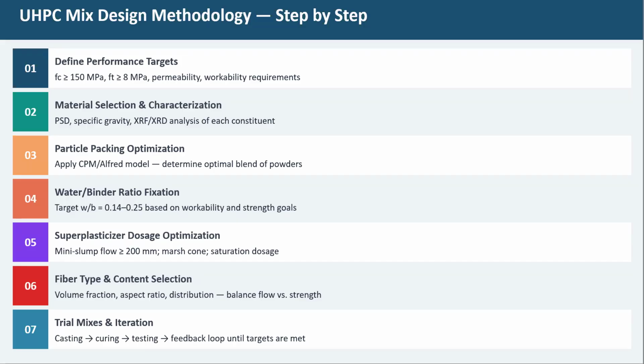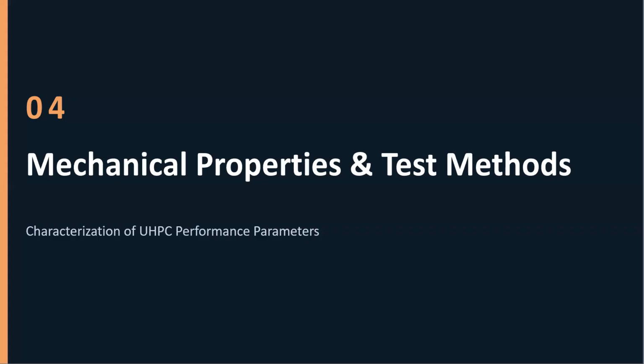That's again a bad sign of flowable nature of the UHPC, where you cannot attain easy flow, especially if you are focusing on self-compacting UHPC. And it is imperative to do multiple trial mixes, because it's not that in one trial we are going to get the entire properties or the desired characteristics of UHPC. It's an iteration of multiple materials, as with any concrete that we are preparing. So it is imperative to do multiple combinations of trial and error, so that only we can finalize the final mix design, followed by which we can take it to large scale testing or field level testing as well. So that's with respect to the mix design methodology.